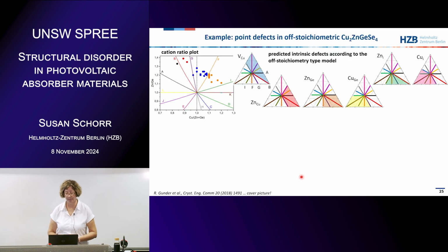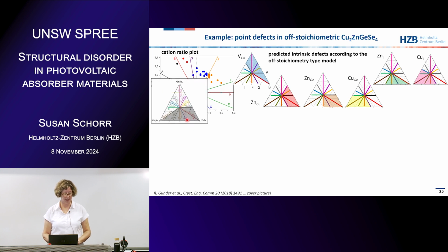This is one example I would like to show you. It's copper, zinc, germanium selenide. Each point here is a powder sample, and this goes from AB type up to I type. So in principle, it covers this area in the phase triangle, and that's why we expect all these defects I have shown here. These are in principle the stability regions of these defects according to the off-stoichiometry type model.